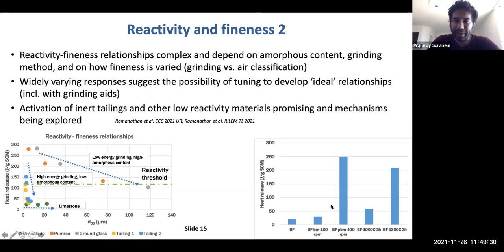Then we put them in a planetary ball mill, which is similar to a ball mill, but its operation is somewhat different. But the big difference is that the rate is 400 RPM. So there's a lot more energy that is being put into the basalt fines. At 400 RPM, you actually get activation, right? So the heat release is 250. Remember, our threshold is about 120 or something like this. So we've clearly now passed a certain threshold and activated these materials.